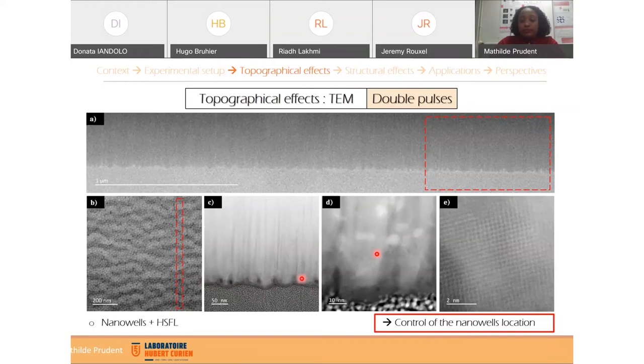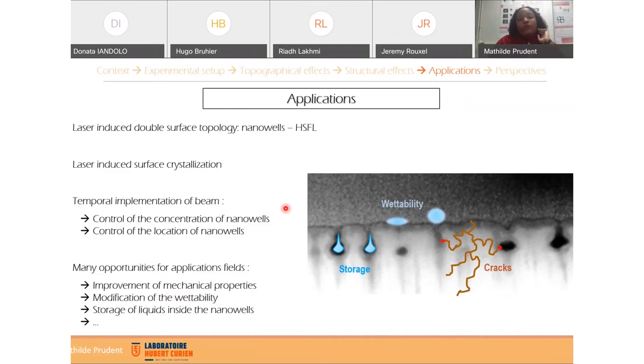So all of these results show us that after femtosecond laser irradiation of metallic glasses in thin film shape, we can create a double surface topology with the presence of nanowells and HSFL, so high spatial frequency LIPSS. We can also, after irradiation, create some surface crystallization. And with a temporal implementation of beam, we can control the concentration of nanowells and also their locations.